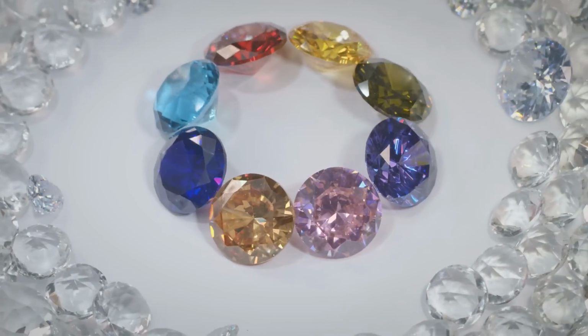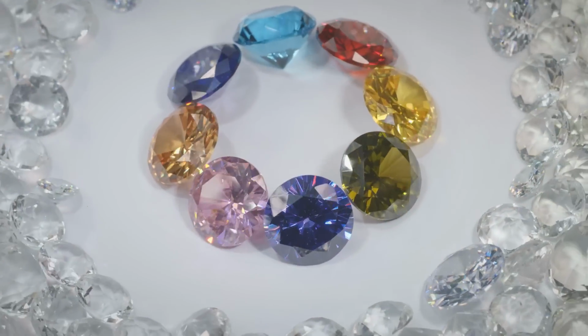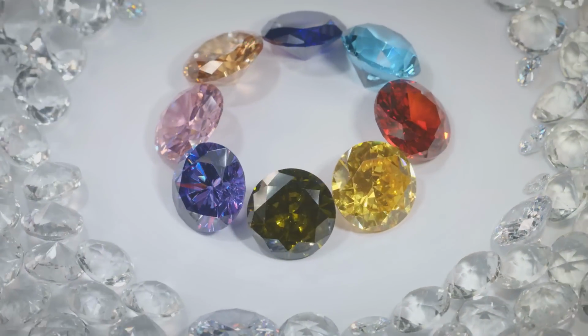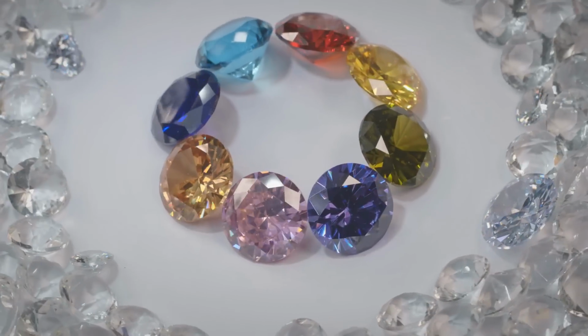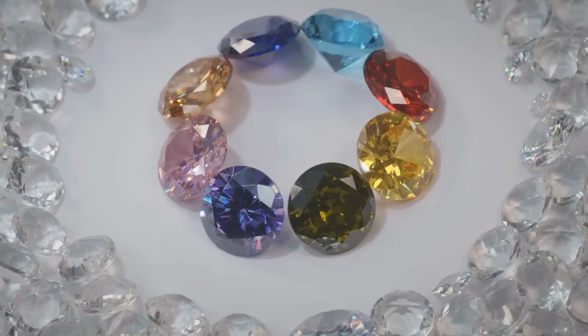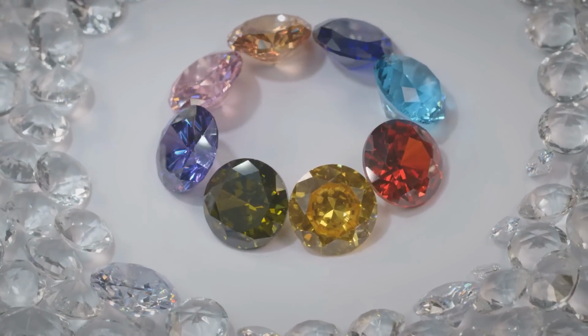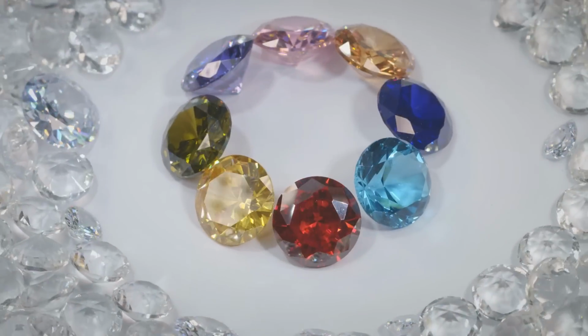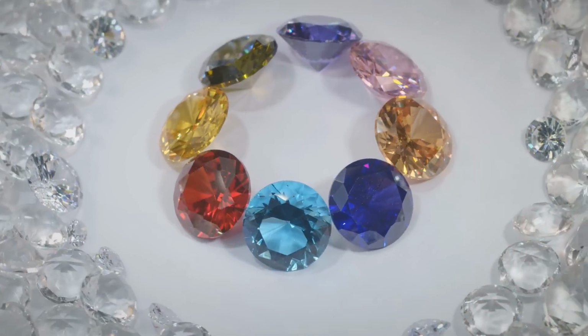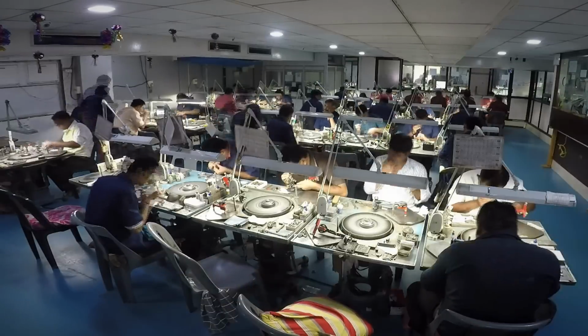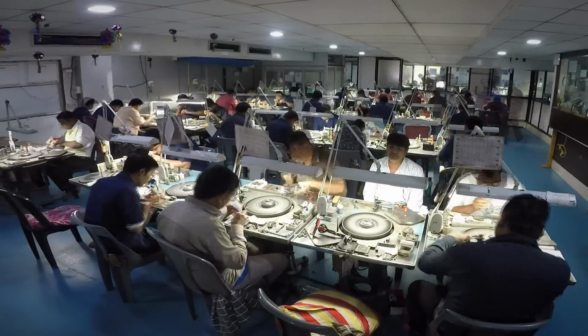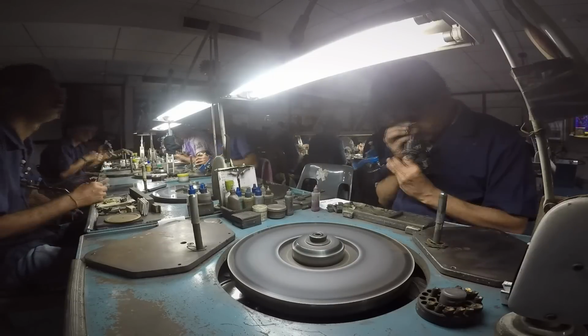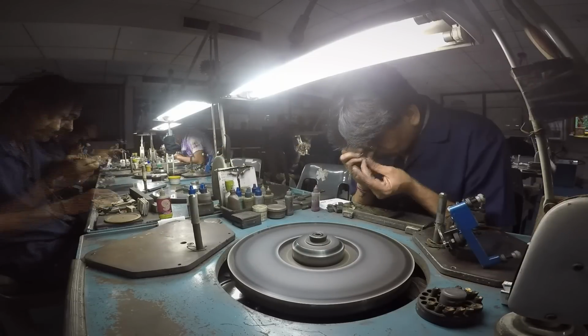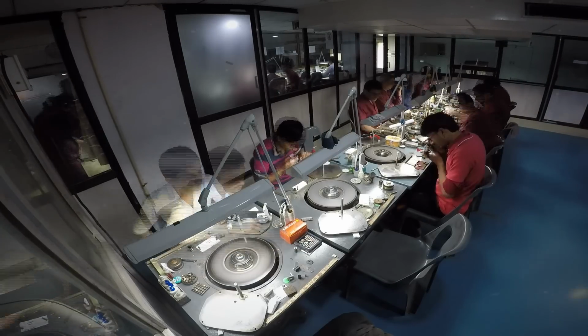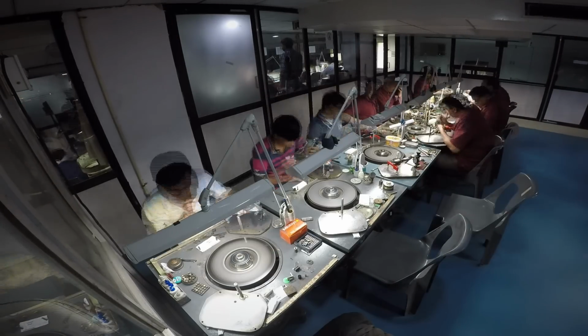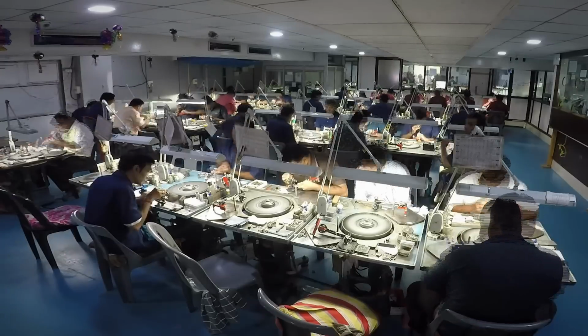At this point, assumptions collapsed. This was no simple fake, no common simulant, and no easy discard. The material was hard enough to resist a carbide scribe, showed directional luster, and had survived direct flame without surface dulling, uncharacteristic of quartz or glass. But it didn't behave like any natural diamond. That's when a third-party analysis was pursued. The specimen was sent to a university geoscience lab with access to Raman spectroscopy and electron microprobe tools. The results brought clarity and surprise.